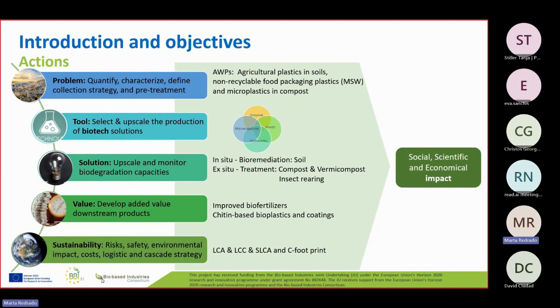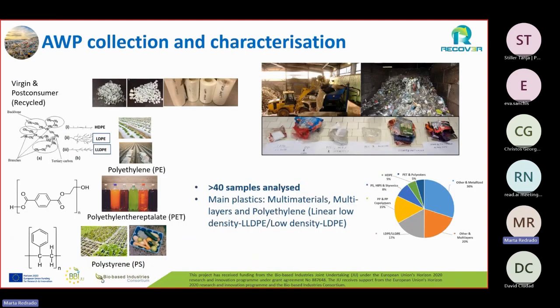Also, in the solution upscaling, we monitored the biodegradation capacities that we tested for bioremediation in soil, in situ bioremediation, and ex situ, where the plastic was treated in compost and vermicompost treatment, and also by insect breeding on the plastic. Then we also analyzed the value of the downstream products. We developed biofertilizer and chitin-based bioplastic and coatings, with the chitin coming from the insects, and we also analyzed the sustainability and the impact of the project in different parts.